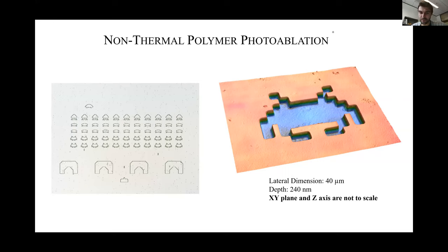The depth is roughly 240 nanometers. It took us about 1 minute to do this etch. And the precision is roughly 10 nanometers or less. So we can really precisely remove polymers with 172 nanometer light. So this was done with contact photolithography, but we can do projection as well. And we will be able to do it in the future.